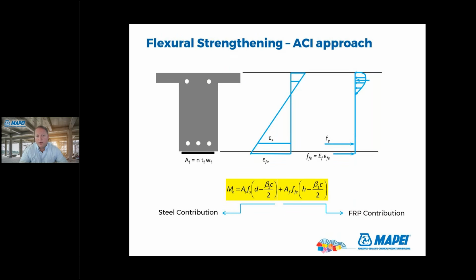Now, the way ACI approaches flexural strengthening is very similar for reinforced concrete as it is for FRP. In reinforced concrete, for calculating the moment, you're looking at the area of the steel times the strength of the steel times the distance of the neutral axis from the reinforcing steel. Similar with the FRP's contribution: the area of the fibers times the effective stress of the FRP times the distance to the neutral axis. Now, looking at the neutral axis on this, you can see the FRP is going to be a little farther away than the steel rebars are. That gives you a little extra moment arm there to help give you a little bump.